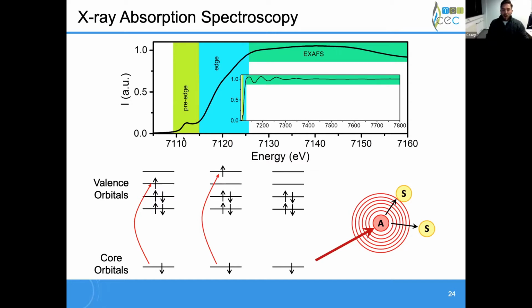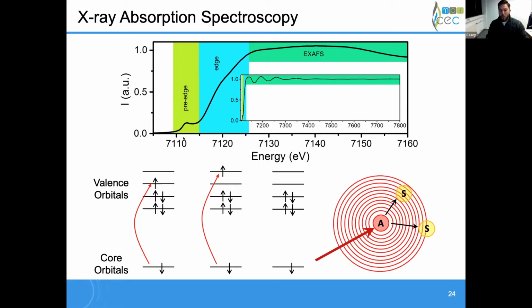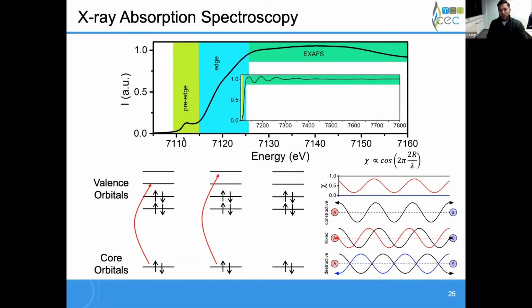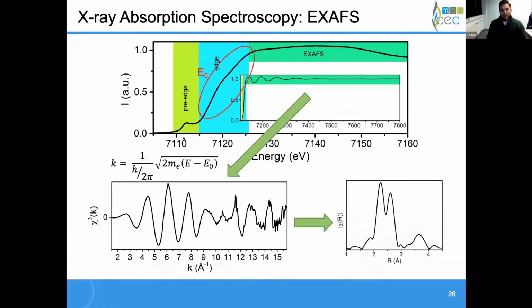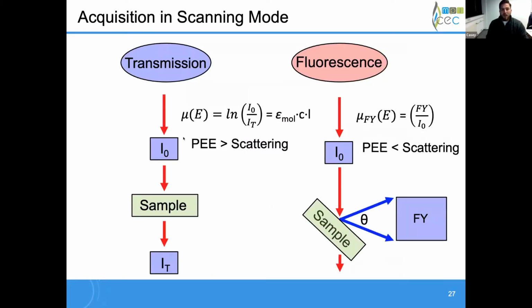Now, when we encounter surrounding atoms, it could either pass through or it could scatter off of those surrounding atoms. This scattering can occur in either a constructive or a destructive fashion. Depending on the nature of the scattering, which is also energy dependent, it changes the probability of this photoelectron being reabsorbed by the original absorber. As a result, we get our nice sinusoidal pattern, which is known as our EXAFS region. From this, we can analyze and fit this data by transforming into k-space, and by further Fourier transform, we can get out structural information about our system: both the identity, roughly, and the distance of these scatterers. Now, this is important for later in the talk, but it seems really simple now.